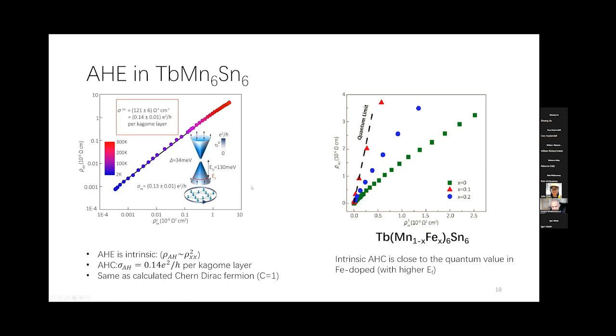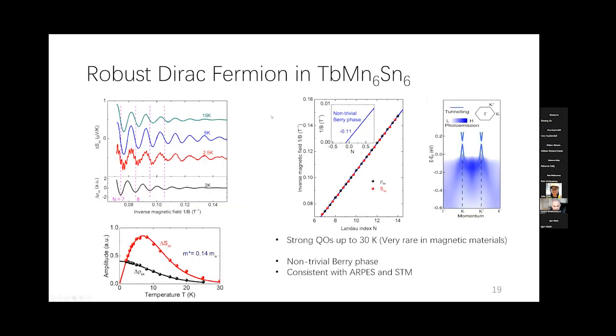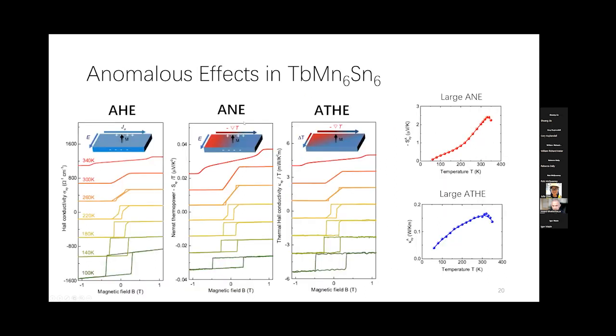the theoretical model as well. We also detected very strong quantum oscillations in terbium 166, even though it is inside a ferromagnetic state. So the quantum oscillation persists up to 30 Kelvin, and you see the effective electron mass is 0.14. Everything is consistent with the band structure calculation and STM measurement. So this result indicates that we have a very robust ferromagnetic ground state from 2 Kelvin to 300 Kelvin, and the massive Dirac fermion is almost unchanged at finite temperature.